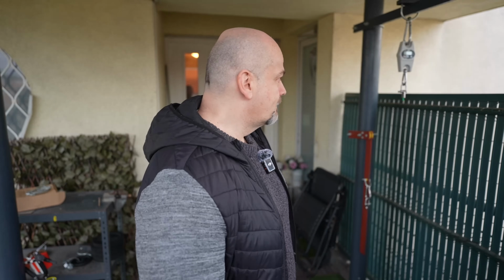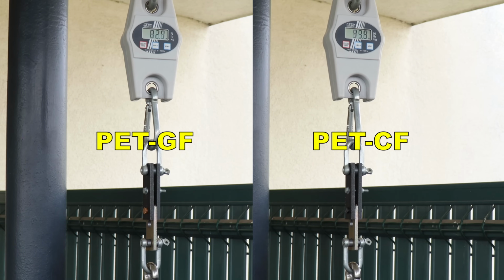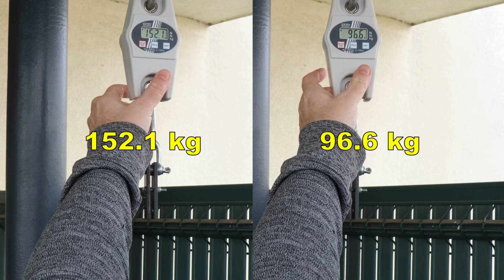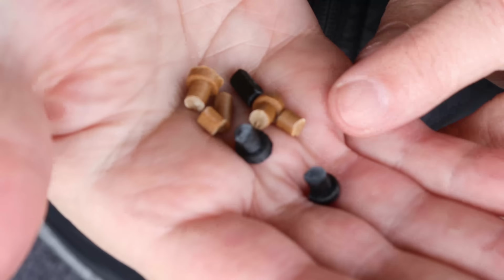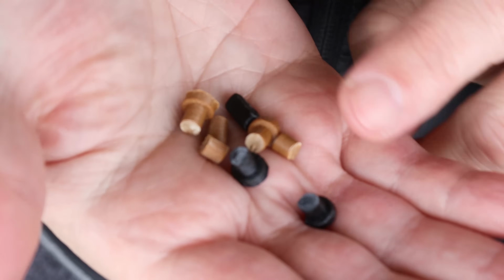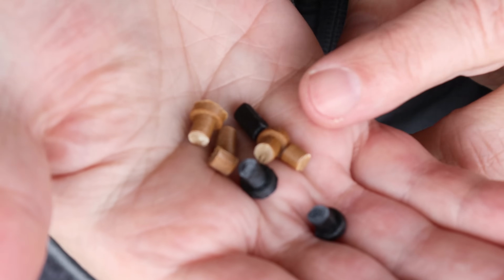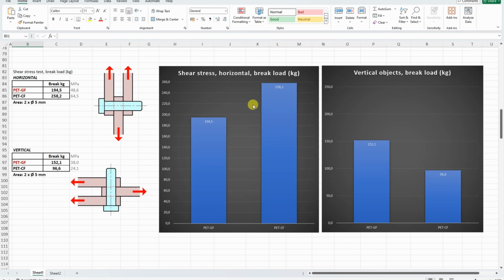Now let's continue. And these are printed in vertical position where the layer adhesion is important. And again, they perform great. This is some serious strength in this material and I couldn't even find all parts. Let's analyze the graph. On shear test, both are incredibly strong materials, but printed vertically, this was incredibly strong thanks to that great layer adhesion, but both are quite good in this test.